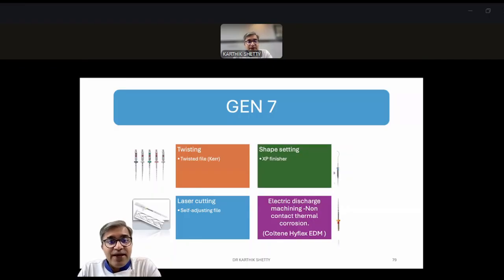Why? Because when we grind NiTi files, the conventional method of manufacturing NiTi, when we grind it, you will create small micro cracks on the surface of the nickel titanium. These will act as nuclei for failure at a later point in time, these imperfections. So to avoid or mitigate this, we have files which have come out with newer ways of manufacturing.